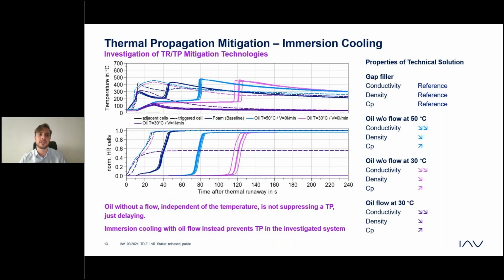Other interesting procedures to avoid thermal propagation would be to have immersed cooling. We have been testing it for different kinds of oils with different temperatures and also with different velocities. The plots are the same here as in the slide before, and you can see, for example, the difference between our standard gap filler, which is the same as before, compared to an oil at 50 degrees, which has lower conductivity, lower density, and a slightly higher CP, that the thermal propagation is delayed compared to our base case.